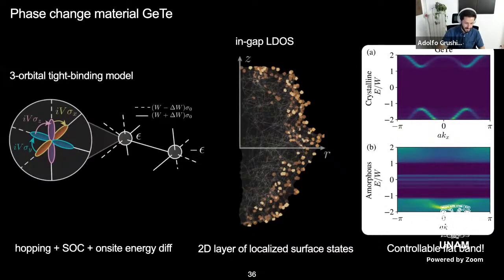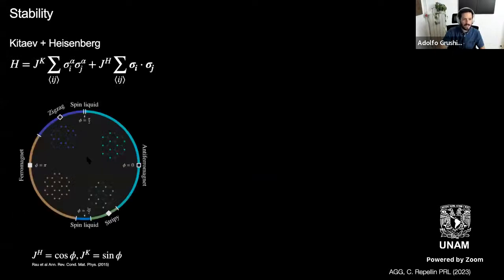And actually, maybe I can show a plot here. These phases actually border, if you add Heisenberg terms, ferromagnetic phases. Well, maybe not the ferromagnetic one, but the spin liquid also borders other phases like the zigzag or the stripy phase, and these are translationally invariant. So we thought that perhaps the amorphous spin liquid would be more stable than the gapless spin liquid.